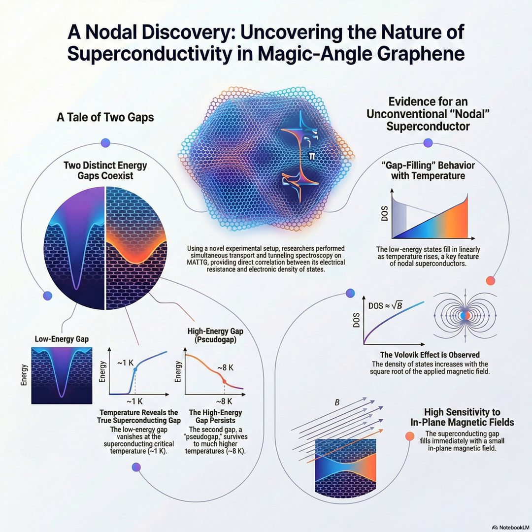By applying a DC bias voltage across that barrier, they could measure 2 things at once. Okay, what were they? First, the density of electron states, vertically, through the tunnel. And second, they could simultaneously measure the electrical resistance, the transport, laterally within the MATTG layers themselves. So that simultaneous measurement just eliminates the ambiguity entirely. Completely. They established a direct, undeniable link between the energy states they measured vertically and the zero resistance state they measured horizontally, all in the same spot. That's the real experimental breakthrough. They built the perfect diagnostic tool.